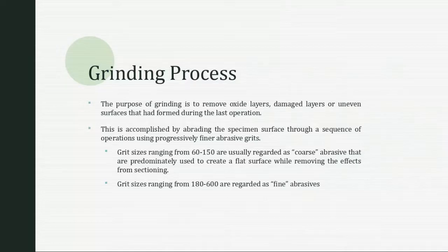To get started, the grinding process purpose is to remove any of the oxide layers, damaged layers, or uneven surfaces that were formed during the last operation. So if you just mounted your sample, your job in the first step is to grind through whatever sectioning technique you utilized. If you used a bandsaw, the damaged layers are deeper, and you'll have to grind through your sample more to get to undisturbed metal.